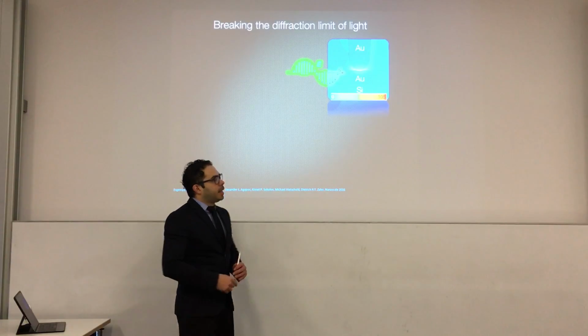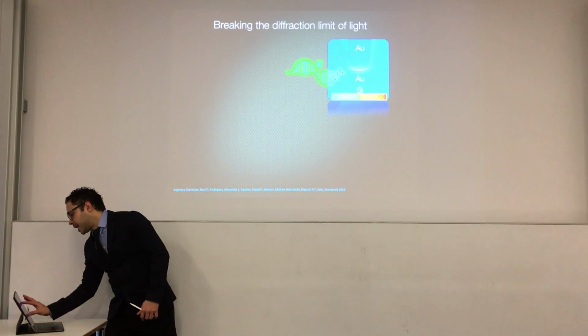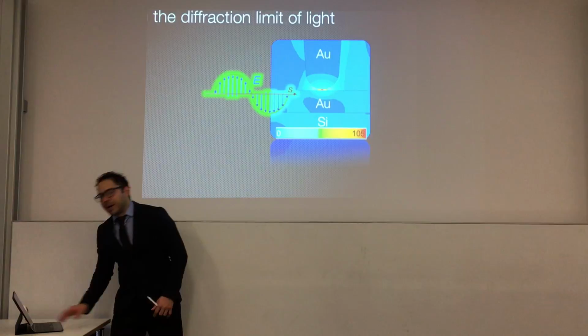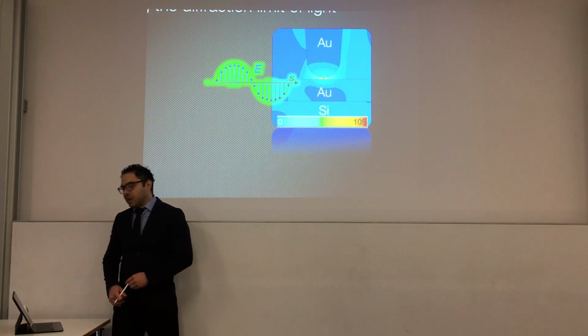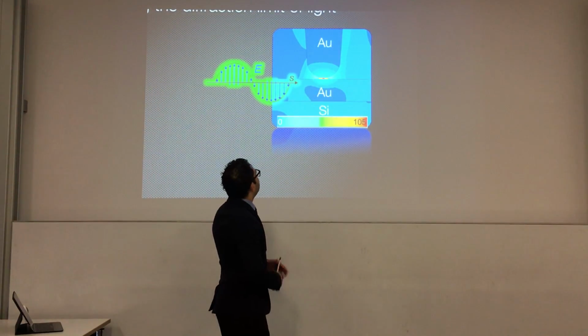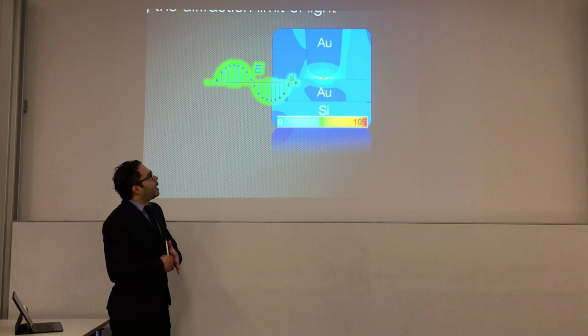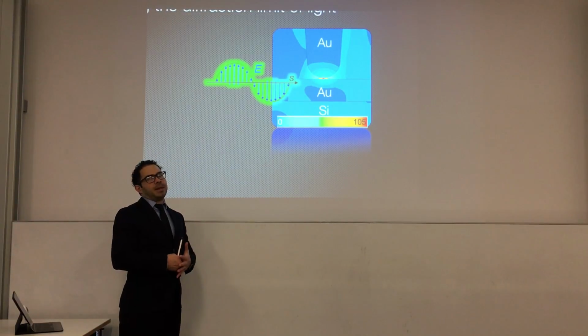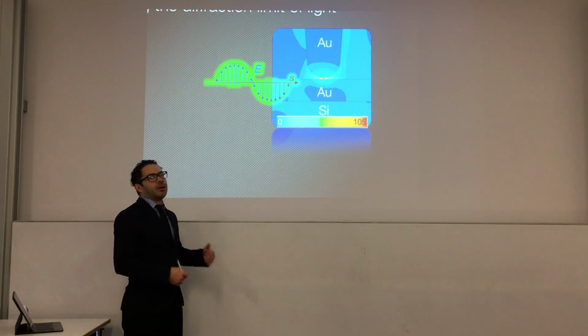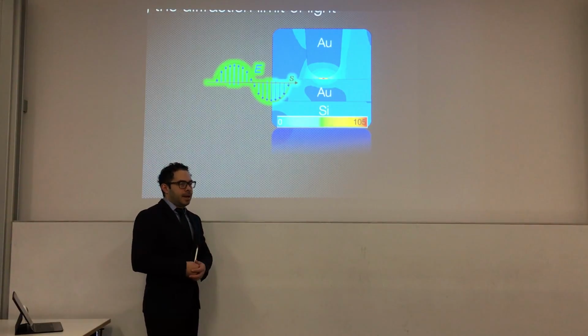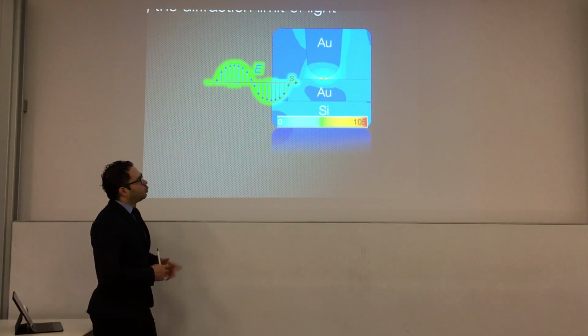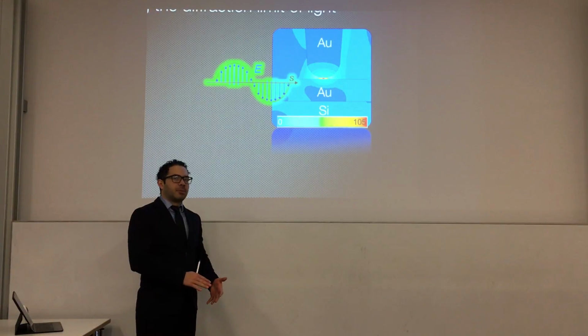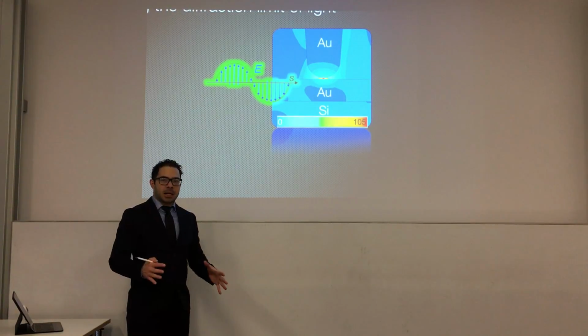You can see that the electric field can go as high as 100 times more. So you have a concentration of the electric field between the apex, an amplification, and a spatial confinement. And this is the beauty of plasmonics, and particularly of tip-enhanced nano-optics: it allows you two things, amplification of the electromagnetic field and the spatial localization.